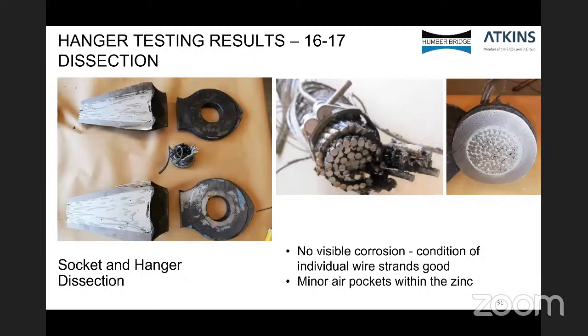As part of the Humber Bridge, one of the things that contributed to the failure of those hangers was misalignment of the socket with the cable, as well as voids within the anchors causing significant corrosion. And for that reason, the hanger socket was taken apart after the destructive testing. It was dissected and inspected. The results of that were very good. There was no visible corrosion. The condition of the individual wire strands was good. There were some small minor air pockets within the zinc metal, but overall it was in very good condition. Go to the next slide.